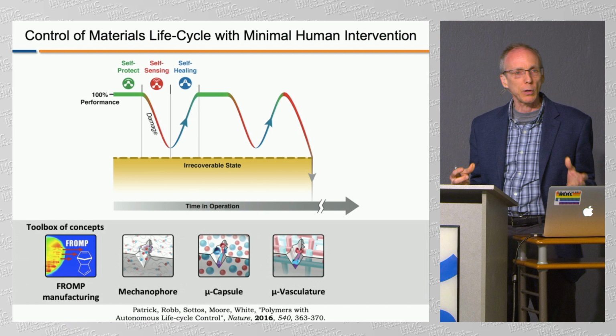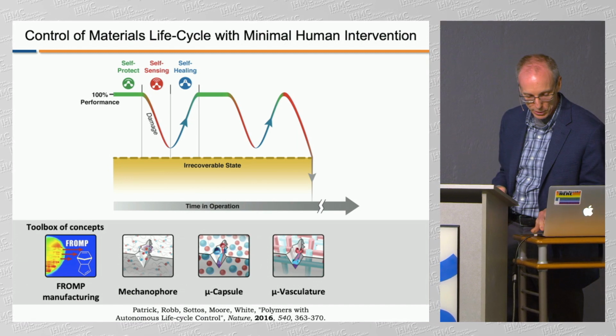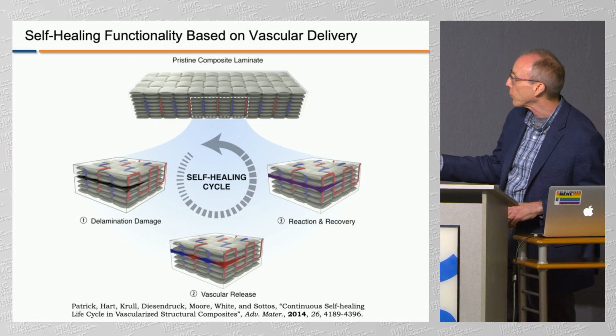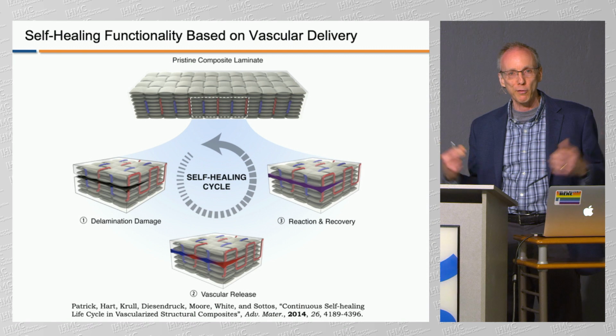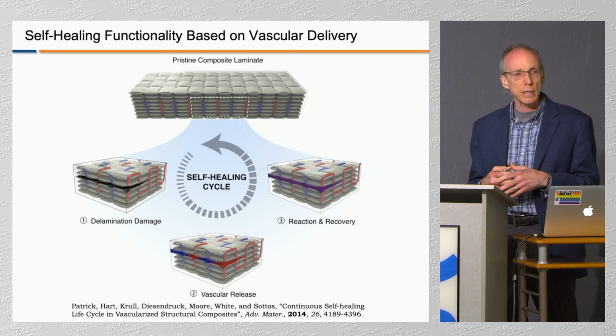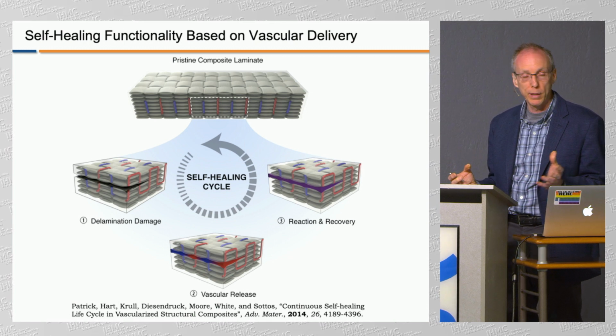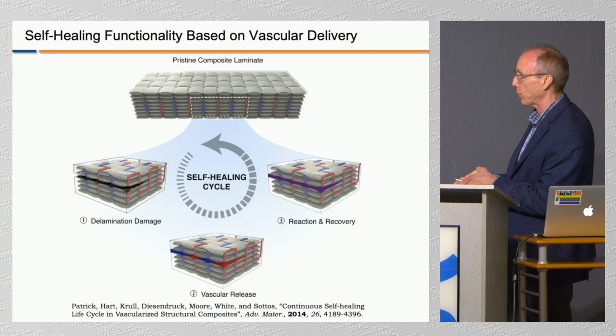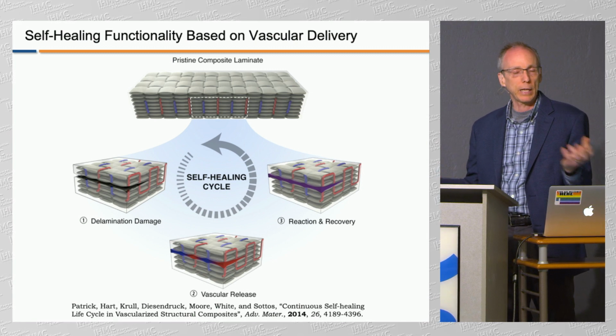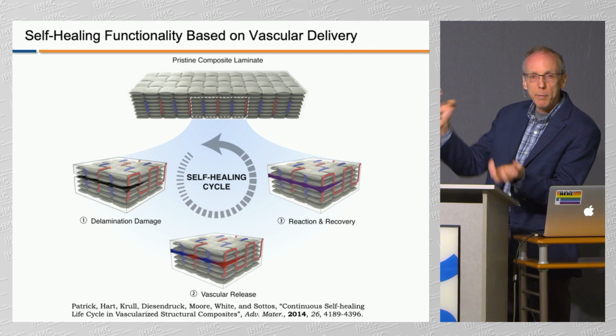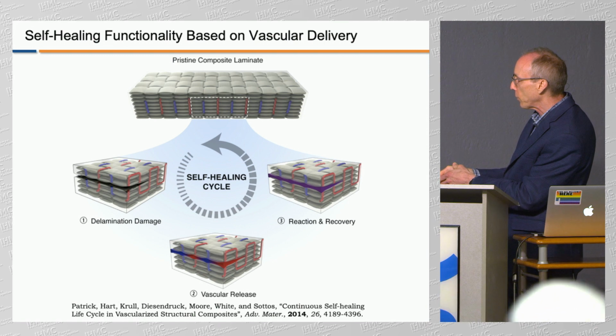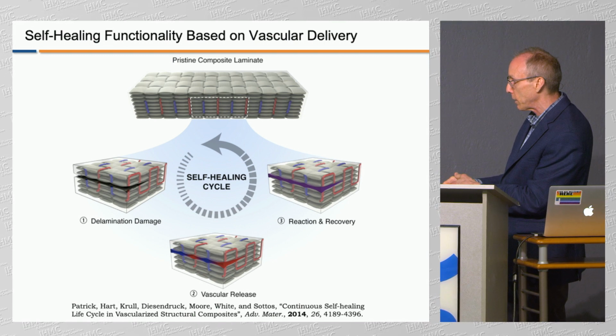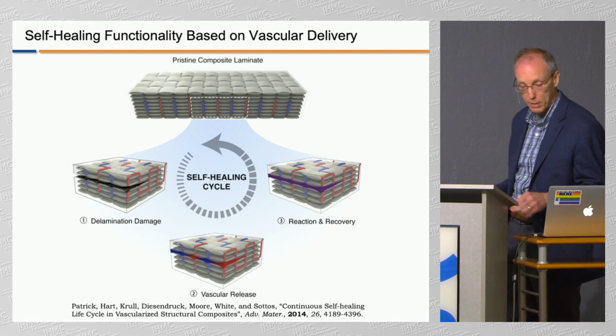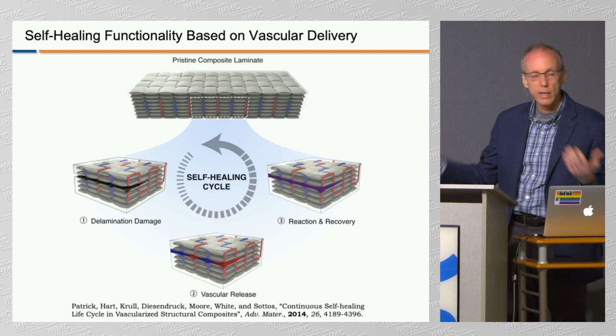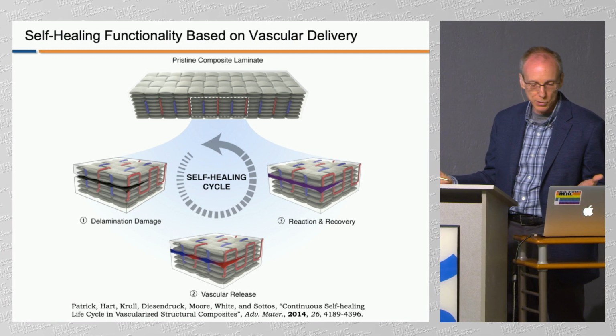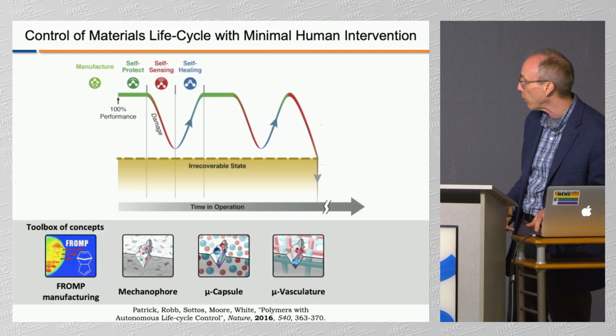Much better than putting the self-healing components into a capsule is a vascularization. And so here's an example of a composite that has been vascularized, much like we're vascularized. And instead of delivering those healing components from capsules that break open, we're delivering those from vascularized structures. And again, red and blue, because we need 2 chemistries that can only come together when damage occurred, so delamination, breaking apart the layers, filling the space, those 2 components mix, and then they polymerize, they rebond those interfaces back together, and we can do this. And the advantage of the vascular structure is that you can repeat this over and over again, whereas the capsules would release their contents once and basically be all finished.